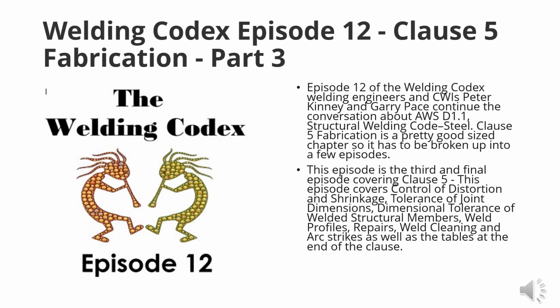A lot of people will use the plug welding method because it's cheap and fast to weld up the hole. However, you don't get through-thickness strength from it, or in tension, usually across the weld isn't as great as the original base material. So there are times when a plug and slot kind of repair is unacceptable as a welded repair, and that comes in when we have tension zones. A lot of times they call it a boat repair, where you weld up half of it, you put a plug in, you weld up half of it, then you gouge out the other half and weld it back up, and you have an elongated boat in the direction of tension. It takes a lot of time on a thick flange, but it's the way to get full guaranteed strength back.